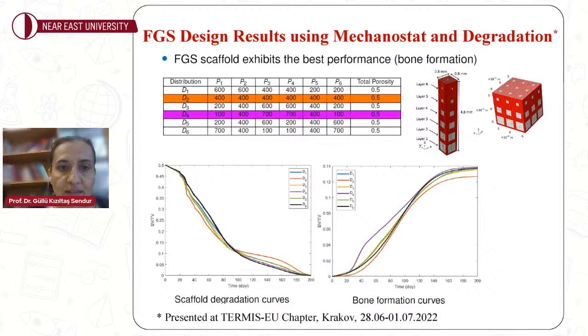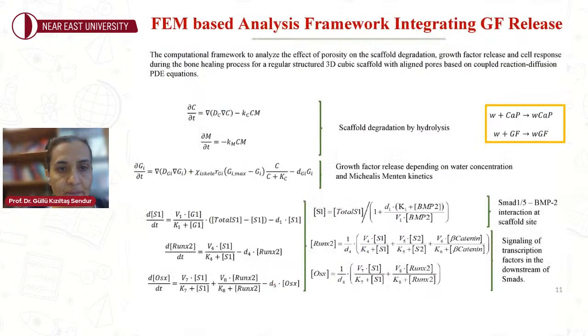Some other functionally graded scaffold design results proved us correct, where we came up with the ideal scaffold being radially gradient, saying that the pores should be larger at the center and come down to 100 microns at the top and bottom layer of a three-dimensional scaffold with square pores this time, based on mechanostat theories and taking into account also the degradation of the scaffold with time.